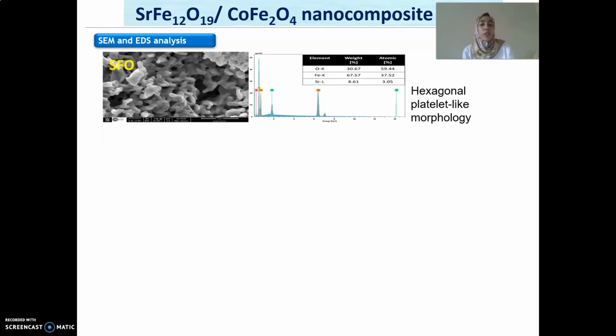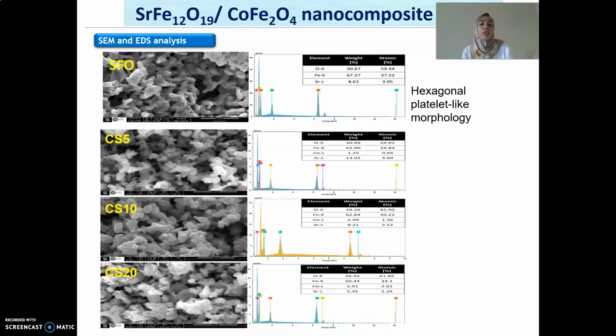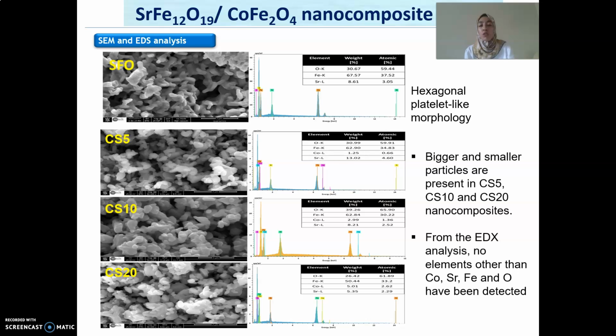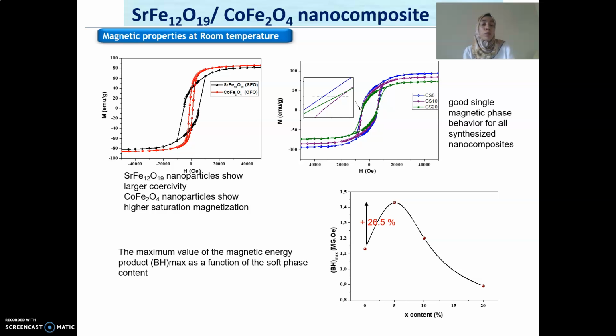The SEM images of the SFO nanoparticles show a hexagonal platelet morphology, while for the nanocomposites we see the presence of bigger and smaller particles, which can be attributed to the presence of cobalt spinel ferrite and strontium hexaferrite nanoparticles. And from the EDX analysis, we can clearly see that there are no elements other than cobalt, strontium, iron, and oxygen in our samples. To evaluate the magnetic properties, we plot the magnetic hysteresis loop at room temperature.